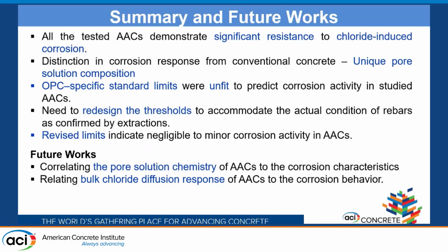To summarize this presentation, all the tested alkali-activated concretes demonstrated significant resistance to chloride-induced corrosion, and this distinction is certainly due to the unique pore solution chemistry of these alkali-activated concretes. However, it was found that OPC-specific limits won't fit to verify the corrosion activity of alkali-activated concrete. Thus, we need to redesign these thresholds to accommodate the actual condition, which was confirmed by our extractions, and the revised limits, which may need further revision, are good in predicting negligible to minor corrosion in our AACs. Further, this work would be correlated with the pore solution chemistry and the bulk chloride diffusion response of alkali-activated concretes to check their impact on corrosion behavior.